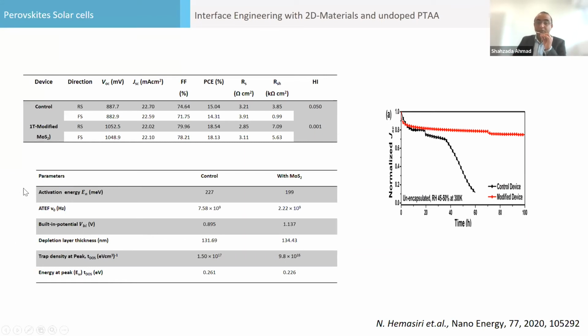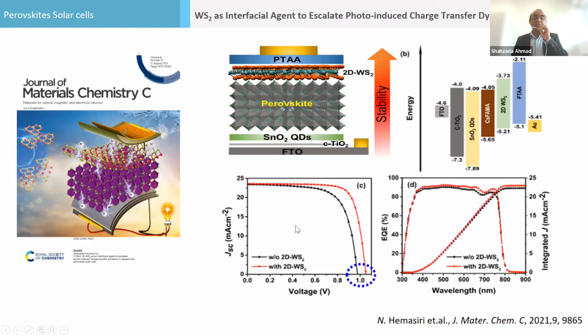But why did this happen? We did a range of electrical characterization, and we found the activation energy is lower, so the charges can move more easily. The attempt to escape frequency also became lower. The built-in potential was higher, and that's why we achieve higher voltage. So this is helping. Now, having learned that MoS2 was working, we repeated the story with different 2D materials; we are in the process of studying them.